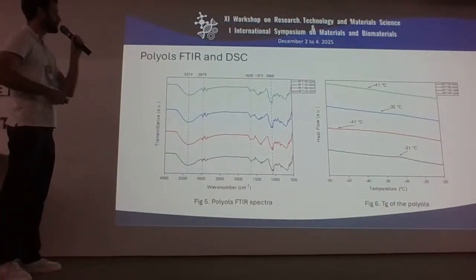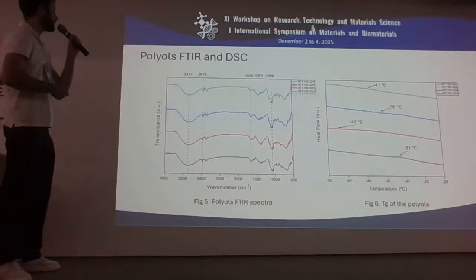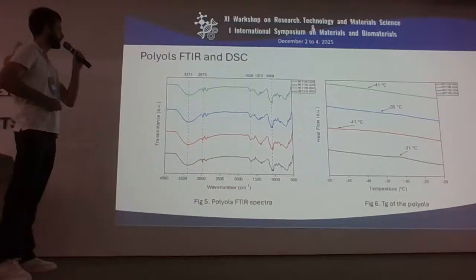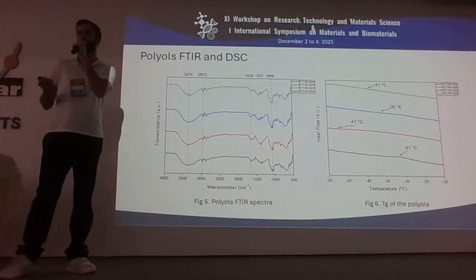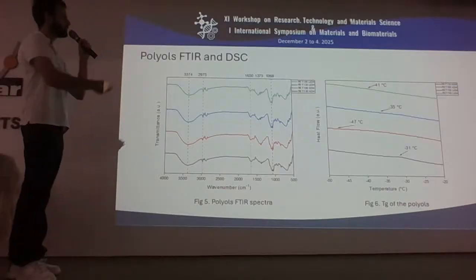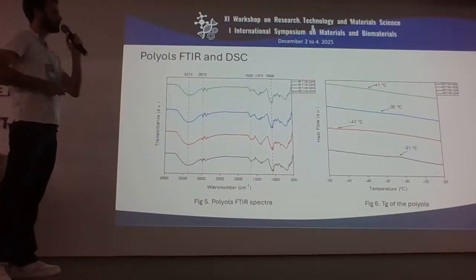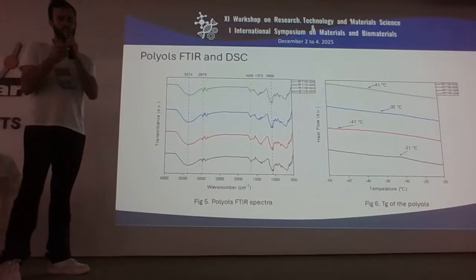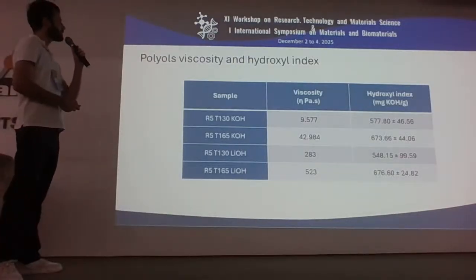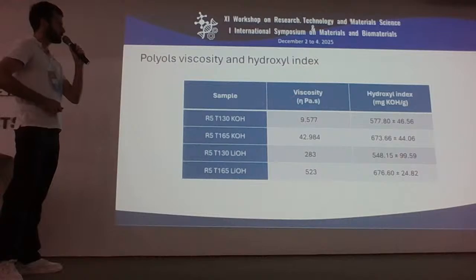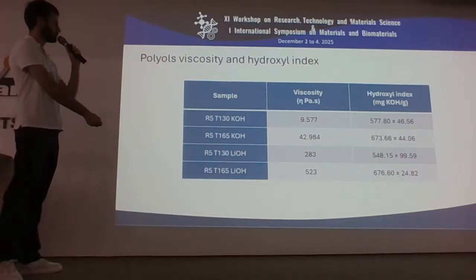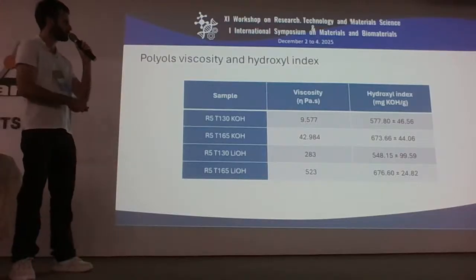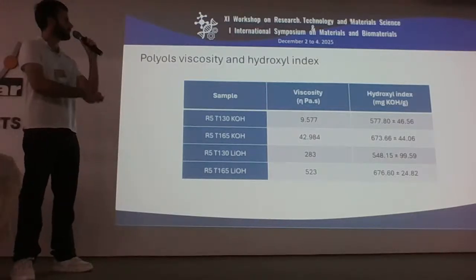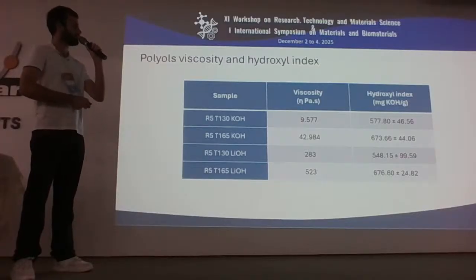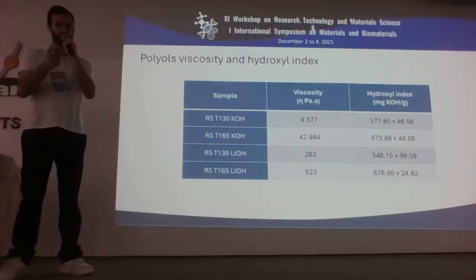So from the FTIR, we can see the polyols were successfully prepared by the appearance of a broad hydroxyl stretching band, which are the active sites that can react with isocyanates to produce polyurethane foams. Additionally, the DSC results show a glass transition temperature between -31 and -47 degrees Celsius, which indicates a low monomer content. For the viscosity of the polyols, we can see that only the sample prepared with lithium hydroxide at 130 degrees Celsius showed a viscosity below 300, which is the limit for application. And the hydroxyl index showed very high values, which indicates suitability for the synthesis of rigid polyurethane foams.